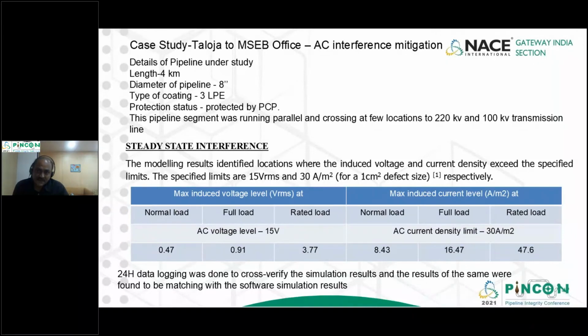This is a case study of an AC interference mitigation between Taloja and the MSEB office, which is a stretch of around 4 kilometers. There's an 8-inch pipeline with 3LP coating, protected by permanent cathodic protection. This pipeline segment was running parallel to, and crossing at a few locations, the 220 kV and 100 kV transmission lines of the Maharashtra state transmission network, and we identified locations where the induced voltage and current density exceeded the specified limits.